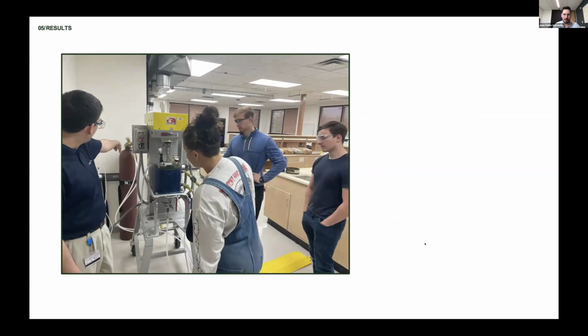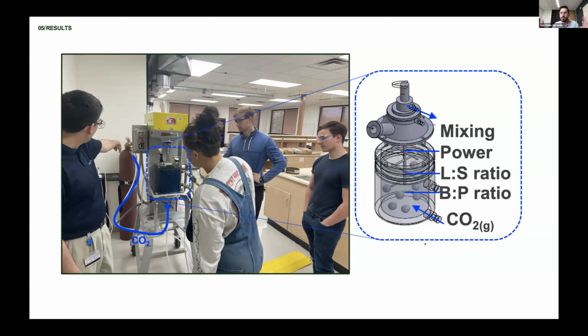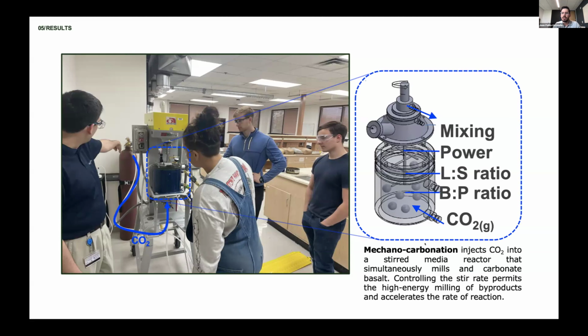What are we actually doing? Let me show you. So with this picture that we just saw, here our senior R&D engineer, Dr. Anand Swathinathan, is pointing to a gas cylinder in the back, which we have retrofitted, and this is our first version of this technology. We're in generation 2 at the moment, so it doesn't look quite like this. But we're able to pump CO2 from the bottom of our stirred media tank. What is happening inside that blue tank right there is that we have a stirred media reactor, which allows us to mill the basalt rock while we are injecting CO2, mixing liquid, gas, and solid phase together to actually not only carbonate the calcium and magnesium in basalt, but also break apart the crystal structure so that it can create a cement replacement.